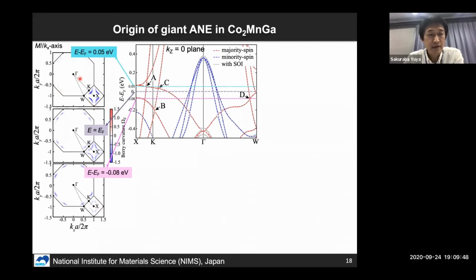And for this calculation, we set the magnetization direction to the x direction. And as you can see, there are several band crossing points near the Fermi level in this cobalt manganese gallium, as indicated by A, B, C, D. And when we include the spin orbit interaction in this calculation, you may see the opening of a gap at each band crossing point on the kz equal 0 plane. So this gap opening appears due to the breaking of time reversal symmetry on this plane.